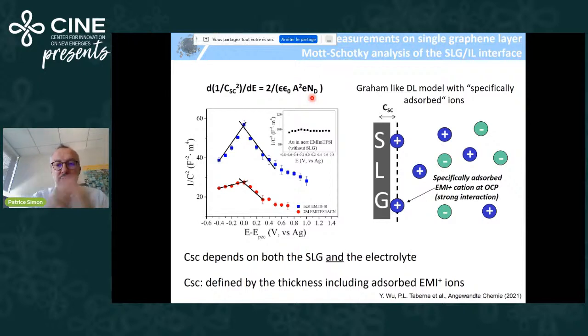But this space charge, because the charge carrier density corresponds to a volume, is a number of carriers per cubic centimeter. We have a 2D material. However, if you remember, we said that we have a strong interaction between the cation and the SLG surface. So in fact, this could be assumed as a Gouy-Chapman-like model with specifically adsorbed ions, and in that case, this is the cation, and this will be here the space charge region. And this space charge region depends obviously on both the SLG and the electrolyte, and is defined by a thickness which includes the adsorbed EMI plus ions.